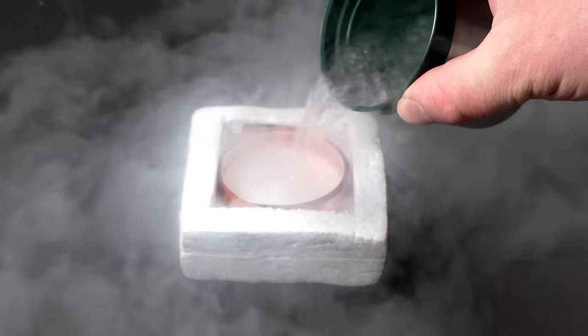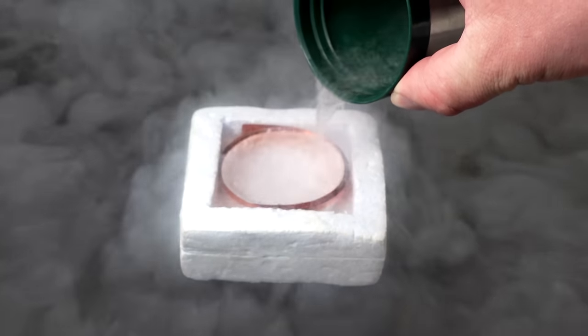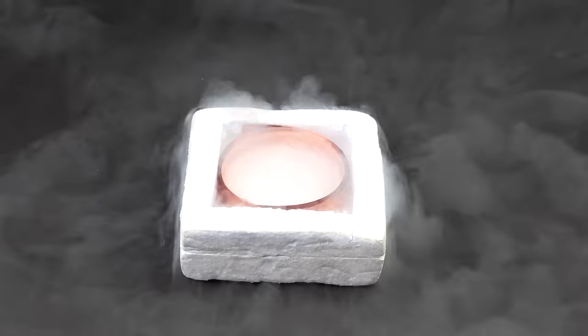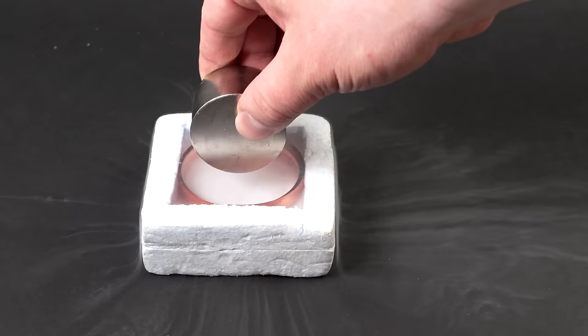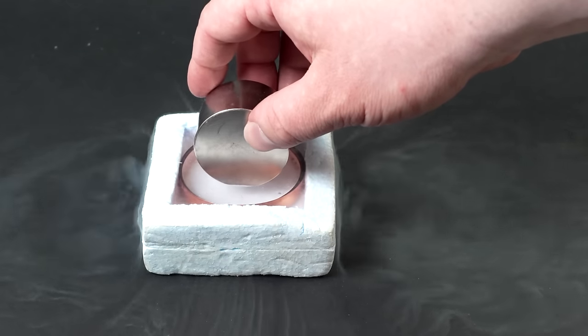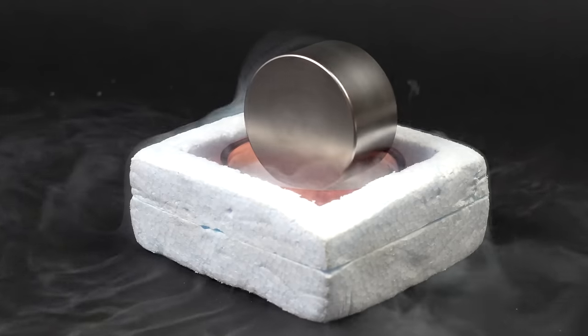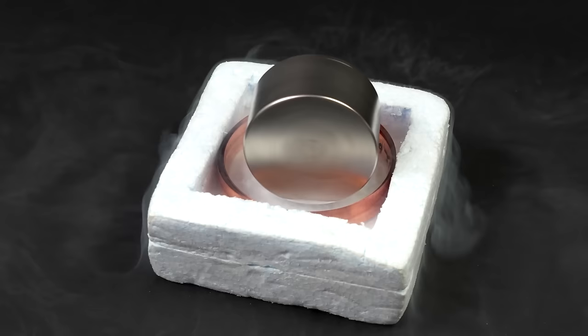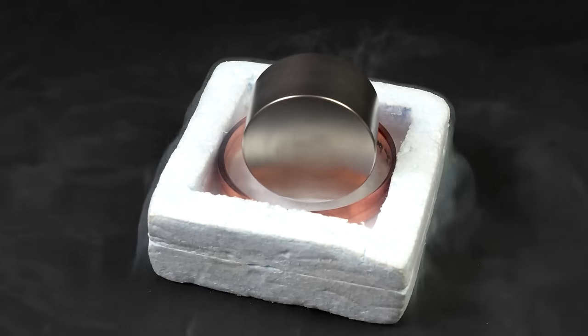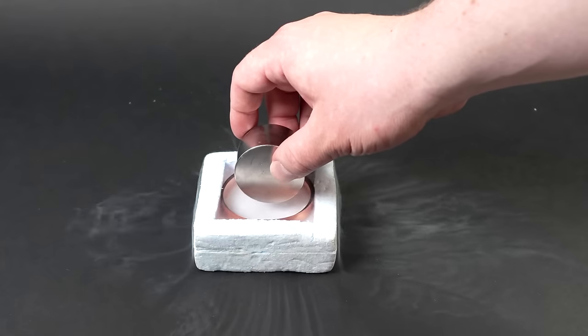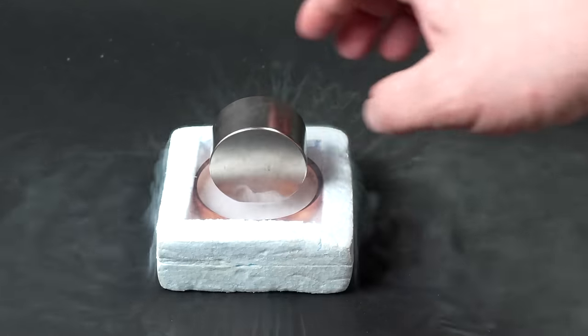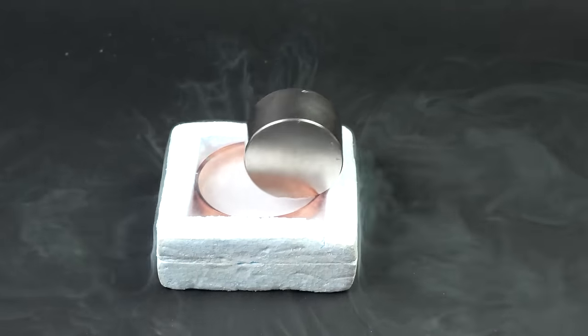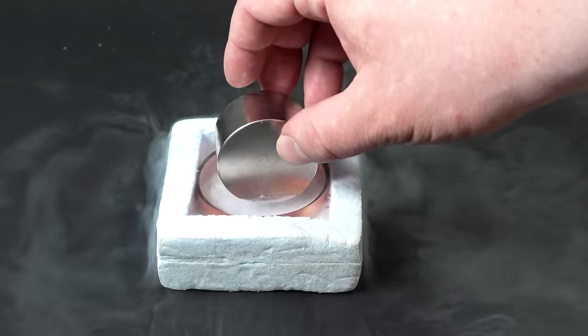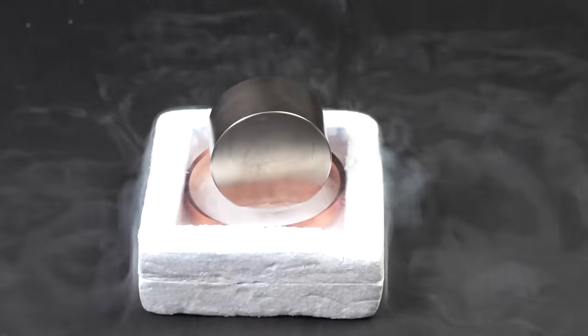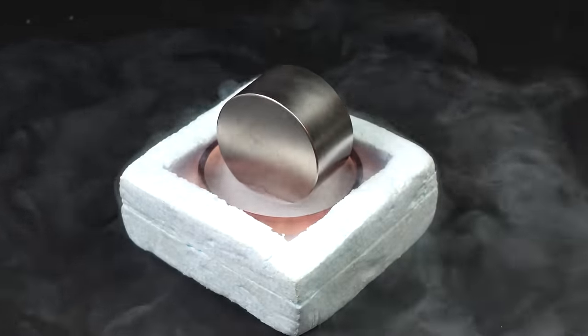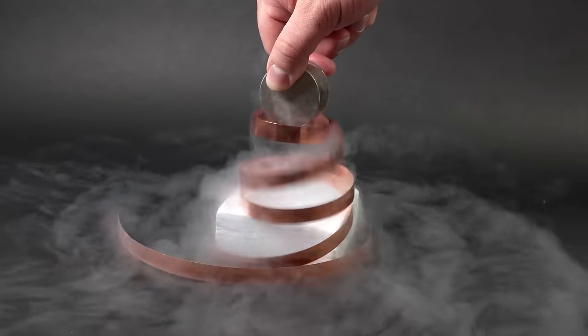The only way I managed to subdue this superconducting tape was to coil it up in liquid nitrogen, thereby creating endless currents and magnetic fields in the tape that could keep the magnet from falling into the nitrogen. Thus, a so-called quantum locking occurred between the magnet and the tape. Quantum locking is a state in which the magnetic field of the superconductor counterbalances the magnet's gravitational attraction to the Earth. It looks quite unusual because even such a thin superconductor tape is able to create a very powerful current within itself, generating its own magnetic field that makes this large and heavy magnet levitate. Obviously, until the tape heats up and loses all of its superconducting properties.